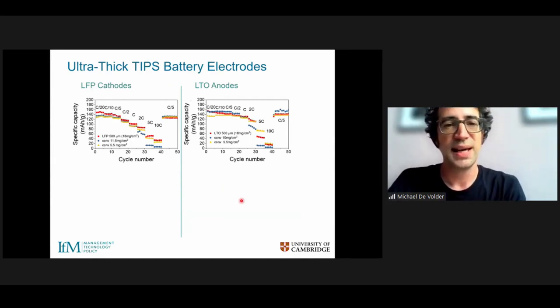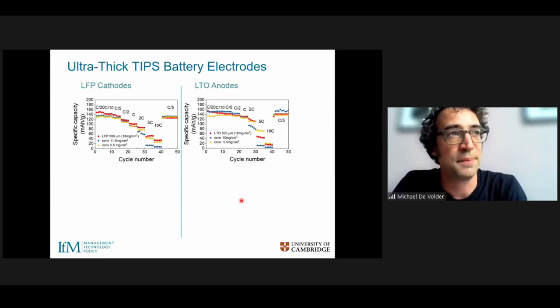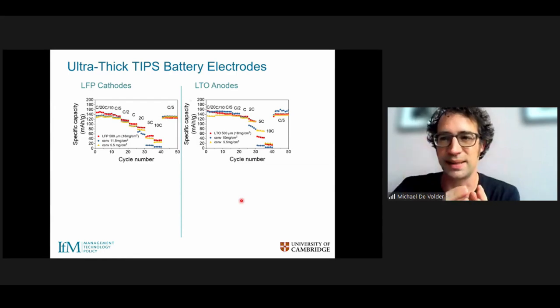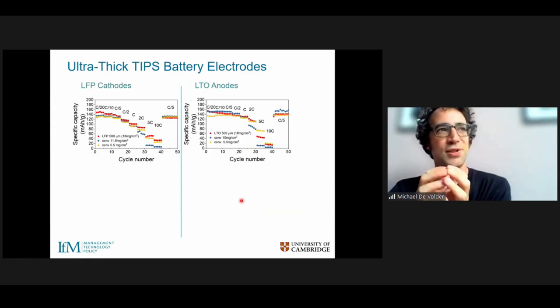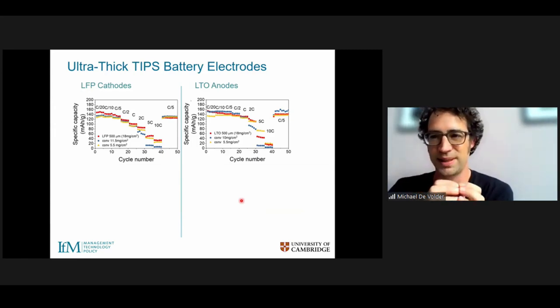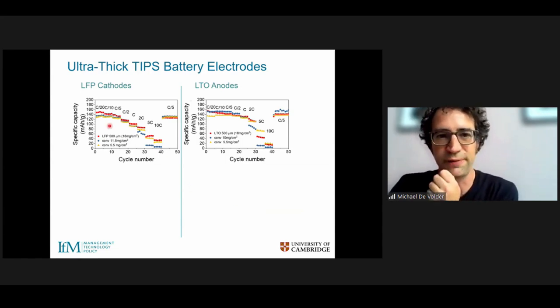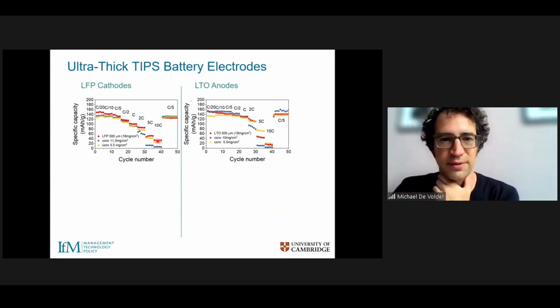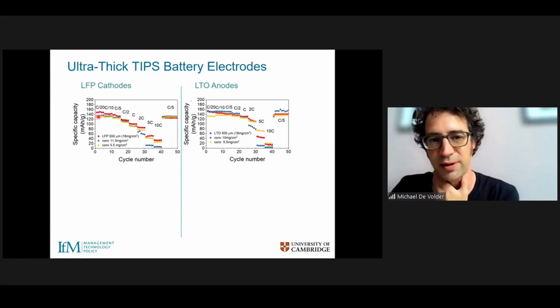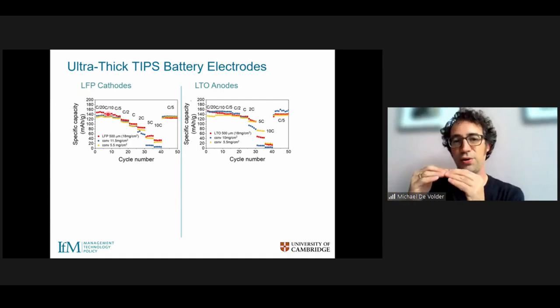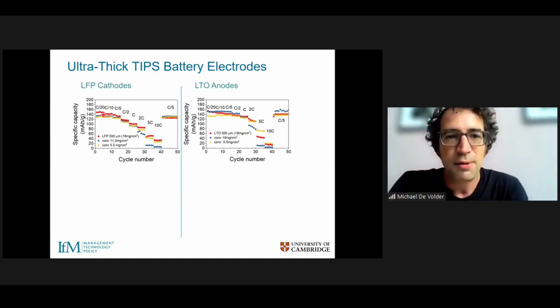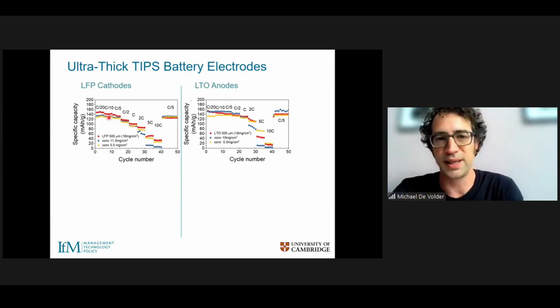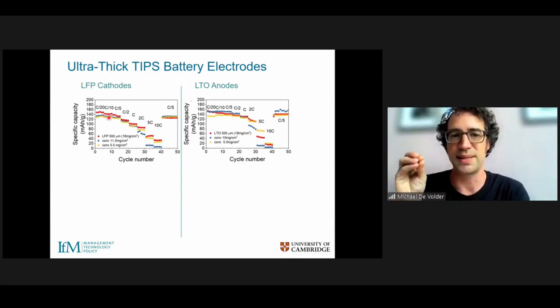And so the first thing we checked is the specific capacity of the lithium-ion batteries. So the specific capacity tells us how many lithium ions we can store per unit mass in a battery material. And so what we've done is in red, we've tested our phase segregated materials here, and we compared them to normal very thin coatings of our materials. So we compare a coating that's maybe 50 microns thick in yellow to one that's 500 micron thick in red. And we can see that despite the huge increase in thickness of our material, we can still store the same amount of lithium ions per unit mass. So it means that the material we are using still performs as expected.